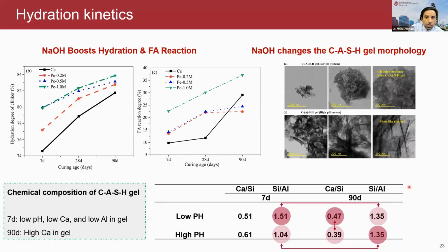We also studied why this happens and what the fundamental changes are when we use this sodium hydroxide in the system. We observe that two things happen. First of all, the morphology of the main binding gel, which we can call the glue in the cement, changes a lot when we use sodium hydroxide. The other thing is that it also changes the chemical composition, our so-called calcium over silica ratio.